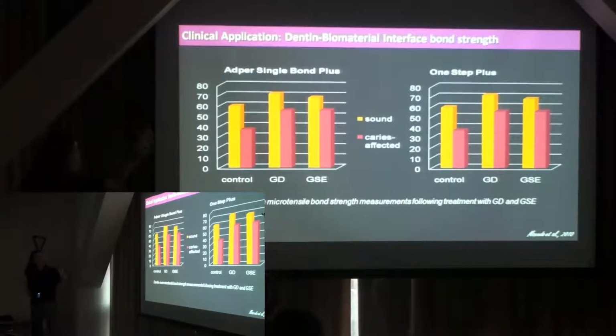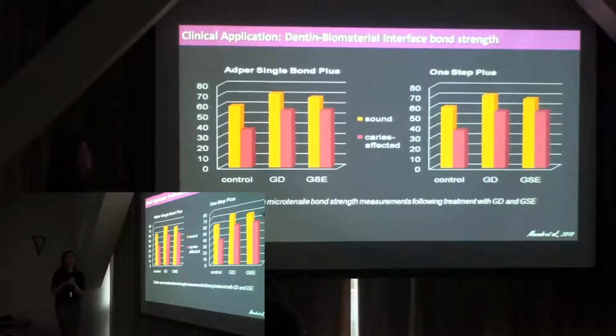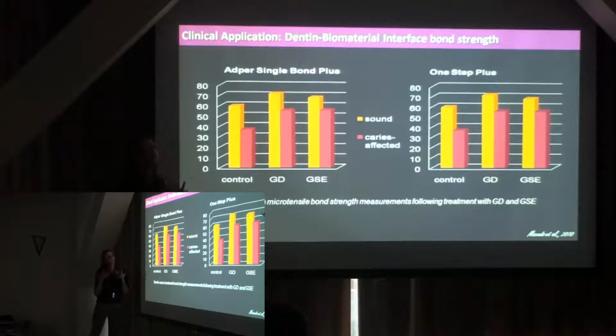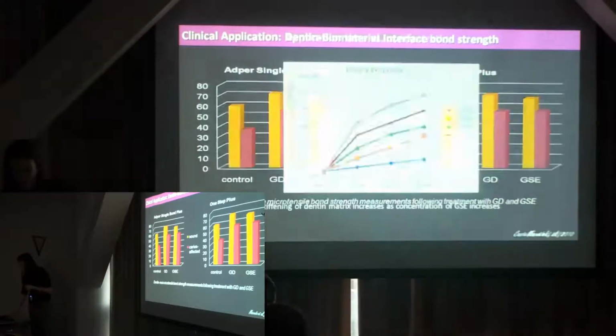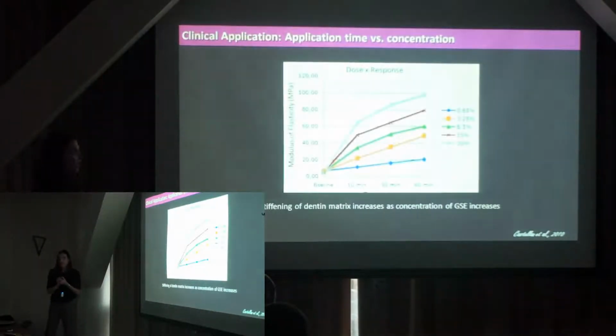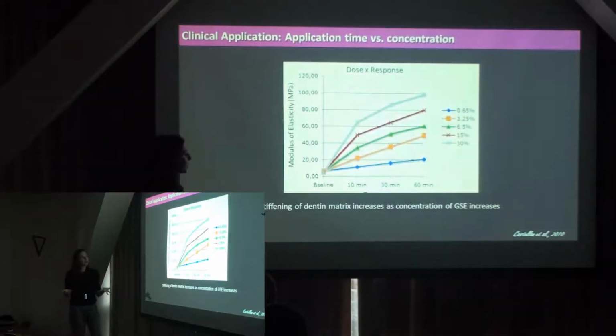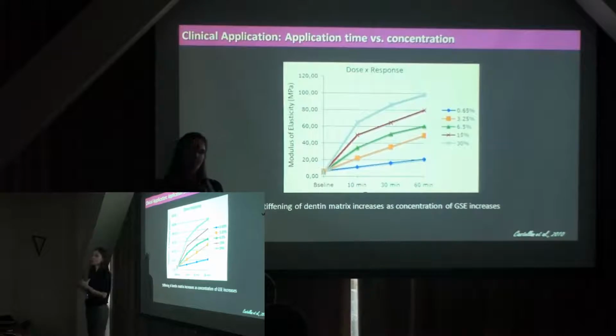The Adper Single Bond and One-Step are 2 different commercial brands of bonding systems that we use. So what we saw is that it wasn't material dependent. It really behaved the same regardless of the material. The problem is that when we started looking at this, we didn't know how long this cross-linking mechanism needed.